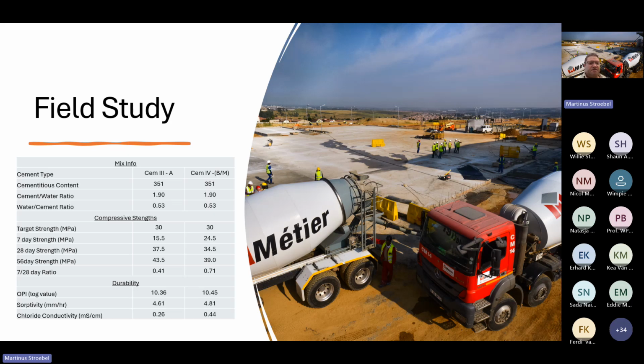He achieves his 70% or 66%. He can strip his formwork. He almost achieves characteristic strength at 7 days. Now, this is good quality concrete. The customer is very happy, and you can carry on with life. When we get to 28-day strength, the customer who got the CEM III definitely got a concrete that is outperforming the CEM IV by 3 MPa, but it's still not bad. It still meets the 30 MPa characteristic strength. Yet this concrete was blamed, and the ready-mix supplier was blamed that we supply poor quality concrete, contrary to the belief. You can see on the screen that there's a massive difference in the 7 to 28 day performance on both these concretes.